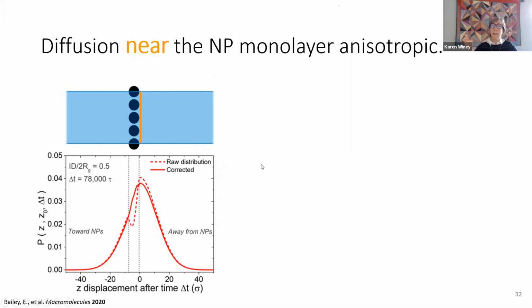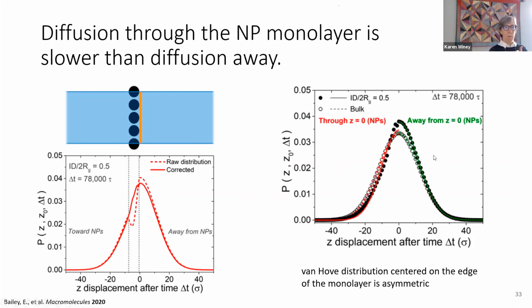But then we corrected the data and normalized it for the amount of available volume. So 100% available over here, 100% available to the left of the particles, but inside these particles, you can do the math and figure out how much available space there is. And still, it's subtle, but that solid curve, the corrected data, is also anisotropic. And so this gives us an opportunity to fit Gaussians to the left and to the right. If we look at the Gaussian going into the particles as opposed to out of the particles, we can get two different diffusion coefficients going in and coming out.